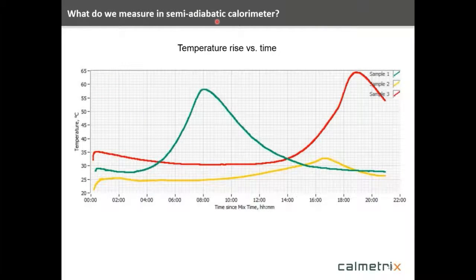So what do we measure in the semi-adiabatic? Well, the curves look very similar. We're basically looking at the temperature rise, but basically it's looking at the concrete curing reaction. So the curves look different, but the semi-adiabatic is considered a qualitative technique. So we cannot integrate under the curves, for instance, to calculate the total heat of reaction. But we can glean a lot of qualitative information from the shapes of the curves and comparing one curve to the next and so forth. So that's what we measure here. We're looking at temperature as a function of time.